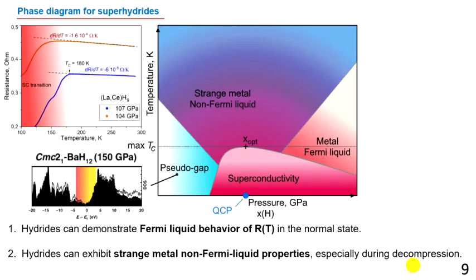Considering all above mentioned, we can build a qualitative phase diagram for polyhydrides. You can see it on my slide, and this qualitative phase diagram will consist of 4 different fields. And instead of level of doping, we can use pressure, which can be easily determined in experiment. At high pressures, hydrides will demonstrate Fermi-liquid behavior. At low pressures, we will see pseudo-gap phase where the temperature coefficient of electrical resistance is negative and the material behaves as a semiconductor. We saw it in H3S and we saw it in lanthanum cerium hydride.